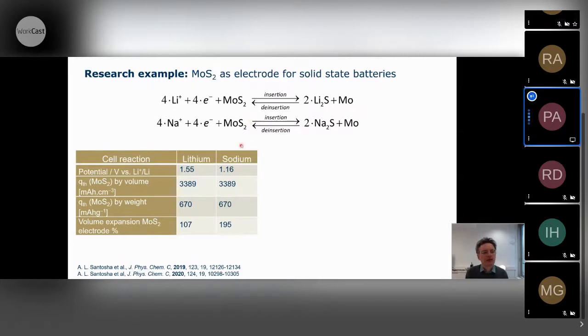The good thing about it is that you can use these equations to calculate energy densities, theoretical voltages, and so on, and the results are shown here. If you assume this reaction, then you will have 1.55 volts for lithium and 1.16 volts for sodium. And here you can see some other specifications. The capacity would be very high, of course, but this would be the voltage. And 1.16 or 1.55 volts is something you're not super happy with. It could maybe be an anode material for special applications, but in principle, the voltage is too high for an anode and too low for a cathode. But it's a very nice model system to study a comparison between liquid and solid-state cells.